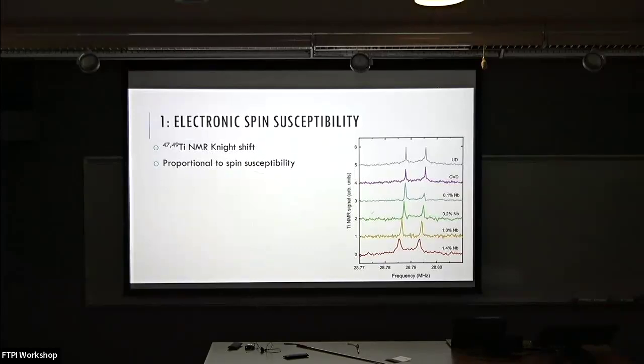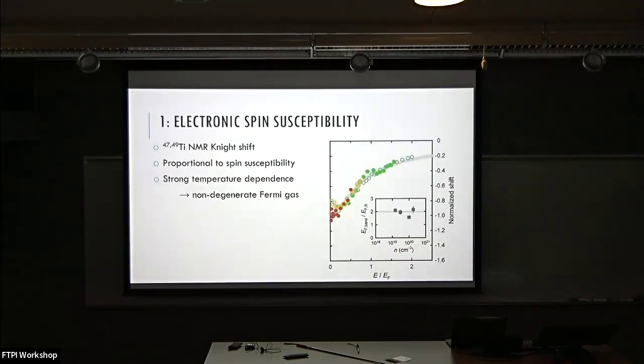And of course, the Knight shift is in principle proportional to the electronic spin susceptibility. So this is a direct microscopic measure of the spin susceptibility, which then can be connected to the effective mass and so on. And this is what it looks like. So what we find is that there is a strong temperature dependence, which is completely consistent with a simple non-degenerate Fermi gas. So that's this line here. This is actually a full calculation, including all three bands and everything, done by Maria. So basically, this is as exact as you can be. And then the only scaling parameter you need to fit your data to this is the Fermi energy. So you can extract the Fermi energy from this measurement without any assumptions.